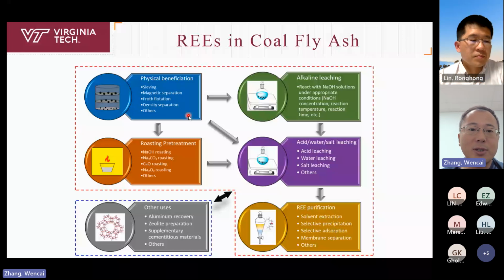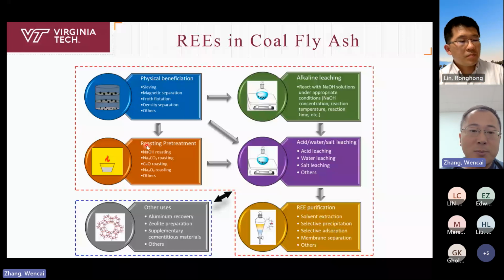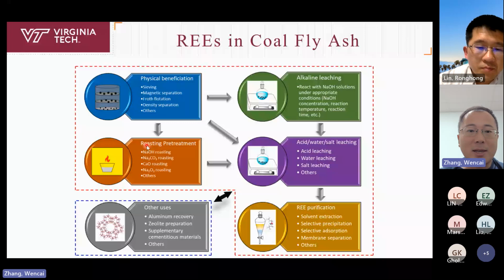The first one, you can do the roasting. So roasting pretreatment is you can roast that fraction with sodium hydroxide, sodium carbonate, calcium oxide, and some other chemicals that can react with the glassy structure. And after roasting, you can do some leaching tests. In this case, after roasting, the glassy structure is already broken, so it can be easily leached into a solution by reacting with acid, water, or salt leaching, and some other lixiviants.